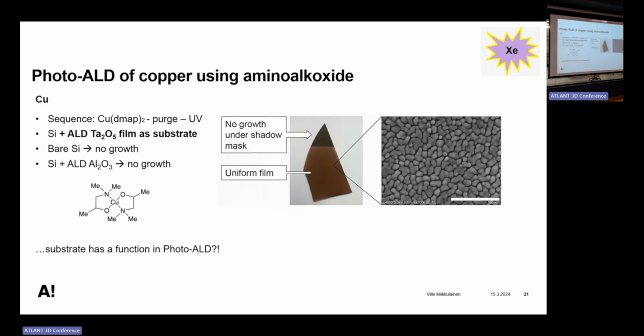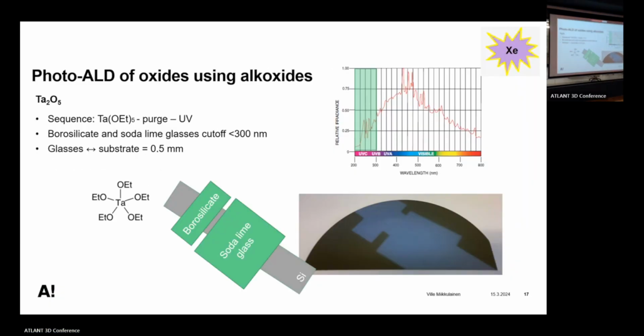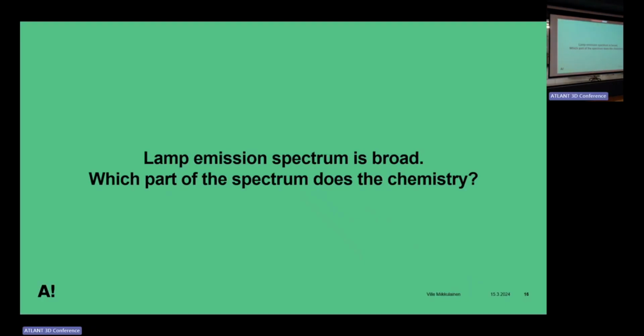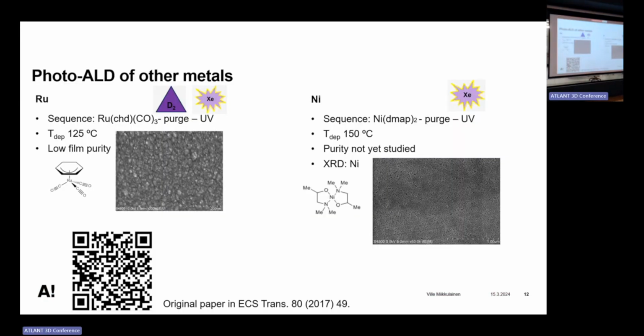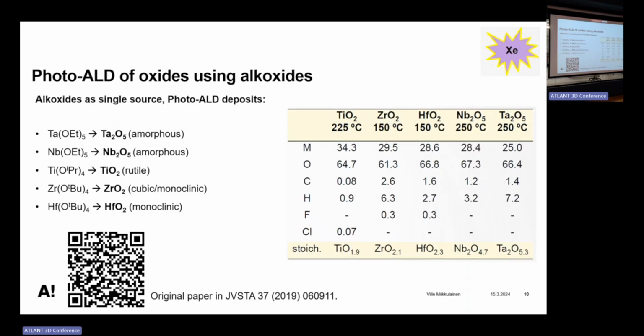My question is, if you start with, say, a tantalum pentoxide film and you reduce that? Not at these conditions. But for niobium oxide, as I mentioned, it is oxygen deficient and denser than bulk Nb2O5, so we could be able to tune the stoichiometry.